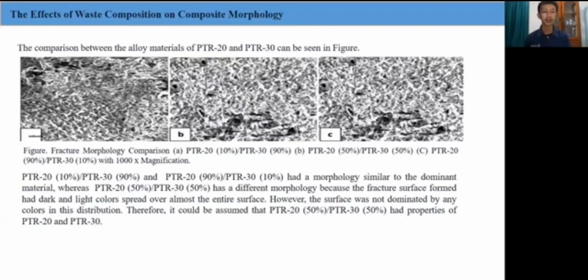PTR-20 (10%)/PTR-30 (90%) and PTR-20 (90%)/PTR-30 (10%) had a morphology similar to the dominant material, whereas PTR-20 (50%)/PTR-30 (50%) has a different morphology because the fracture surface had dark and light color spread over almost the entire surface. However, the surface was not dominated by any color in the distribution. Therefore, it could be assumed that PTR-20 (50%)/PTR-30 (50%) had properties of PTR-20 and PTR-30.